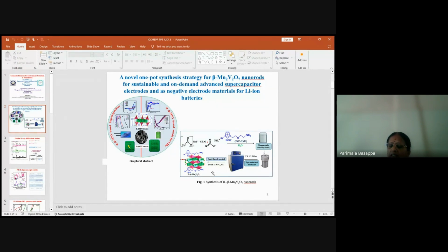We got a brown precipitate of beta manganese vanadate. The same experiment was repeated using this ionic liquid, DOMIMS, that is 1-(3,6-dioxaheptyl)-3-methylimidazolium methanesulfonate. This is the ionic liquid prepared by going through the literature.